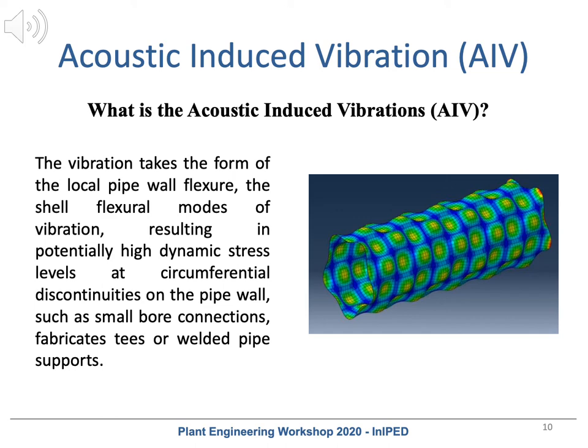Acoustic fatigue is a particular concern as it tends to affect safety-related systems. The time to failure is short due to the high-frequency response, as well as giving rise to high tonal noise level external to the pipe. This form of excitation can generate several high-frequency vibrations of the pipe wall. The vibration takes the form of local pipe wall flexure, the shell flexural mode of vibration, as can be appreciated in the attached picture, resulting in potential high dynamic stress levels at a circumferential discontinuity of the pipe wall, such as a small bore connection, fabricated tee, or welded pipe support.